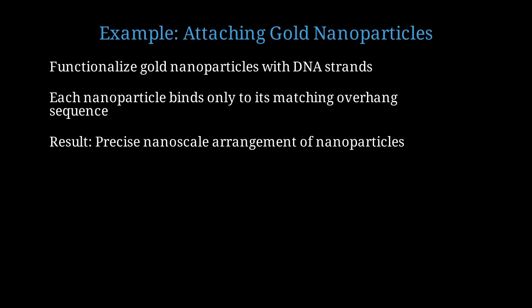We can coat gold nanoparticles with DNA strands that have sequences complementary to our overhang sequences on the origami structure. When we mix these functionalized nanoparticles with our DNA origami, each nanoparticle will bind only to positions with the matching complementary sequence. This gives us precise control over nanoparticle spacing and arrangement at the nanoscale. We can create specific geometric patterns with accuracy better than 5 nanometers.